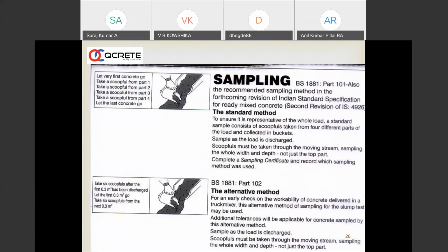There is also another method which is closer to the IS method we discussed earlier. This is also called spot sampling, where they talk about leaving about 0.3 cubic meters of concrete from the truck onto the pump or onto the element, and then you start taking the sample. They specifically say that the alternative method, or spot sampling, is only for checking the slump and not for casting the cubes. So if we want a composite sample, taken for both slump and strength, we have to use the first method, which is the standard method of sampling. This is the only way that we have to do it.